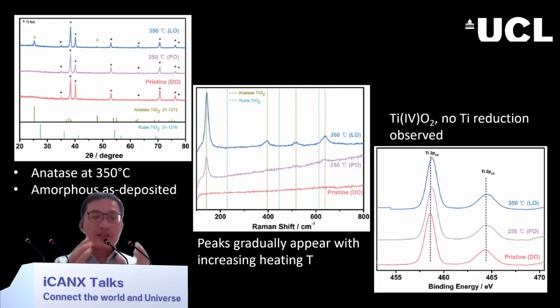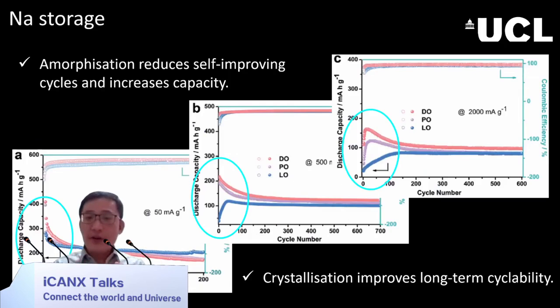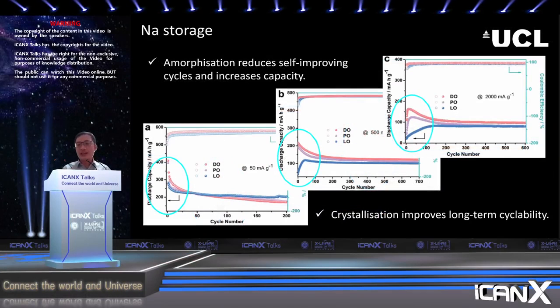We use the three materials all for sodium-ion batteries. And the results are quite interesting, which is different from what we initially expected. So at a lower charge-discharge current, we see that the amorphous titanium dioxide delivered the highest capacity among the three samples. But the cyclability isn't as ideal as the crystalline material.